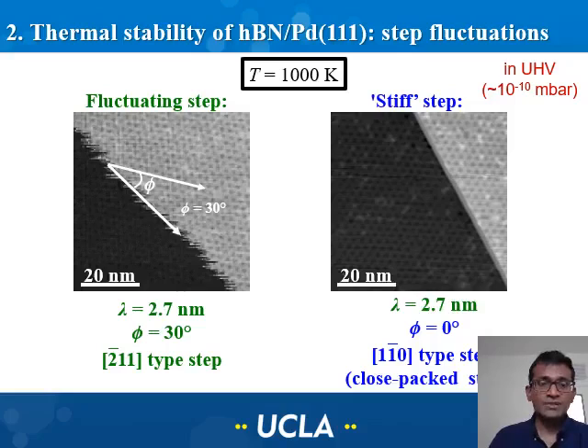From the analysis of the orientation of these step edges, we know that this particular step orientation is a [-211] type on a face-centered cubic palladium (111) surface, and we attribute this to the more stable 110 steps. So the steps that are stable have high stiffness, and so there are no fluctuations in this case, compared to higher energy steps, which have low stiffness and fluctuate more. This is commonly expected, and that's what we observe even with the hexagonal boron nitride.